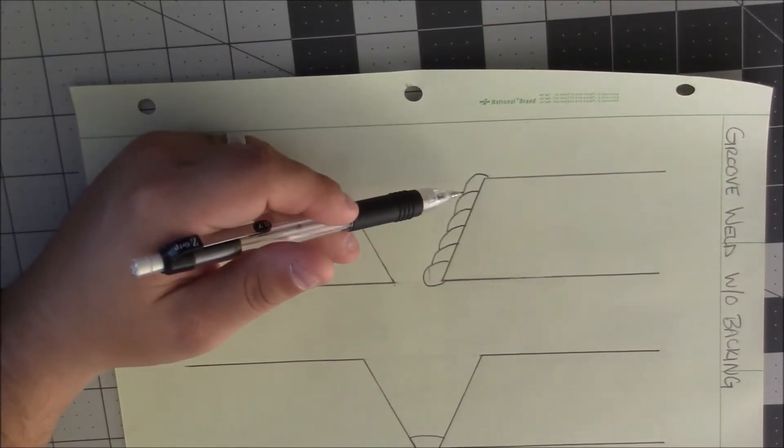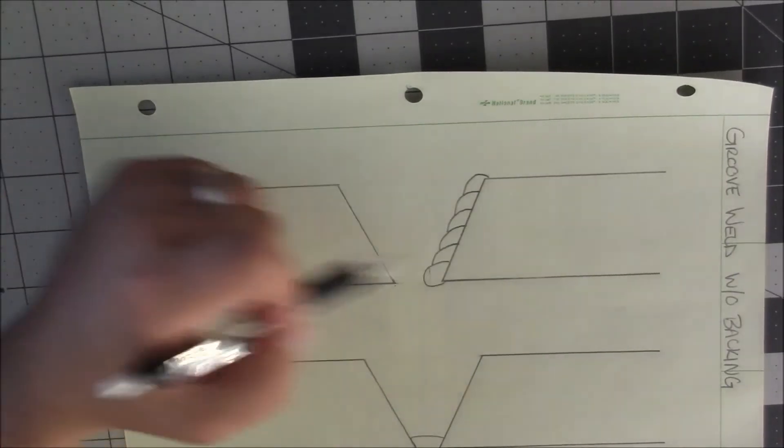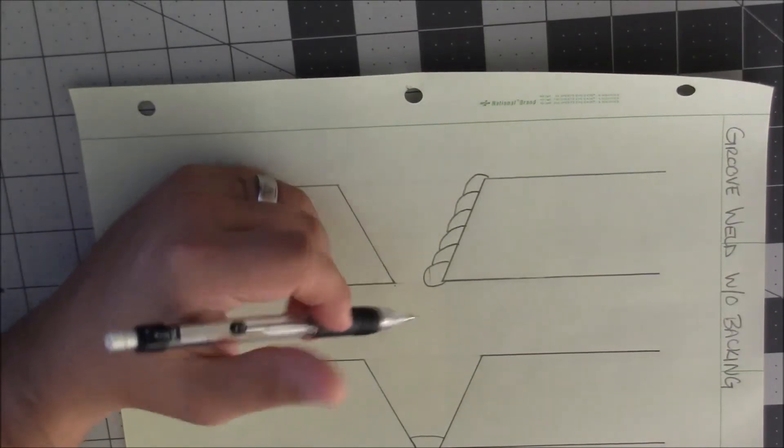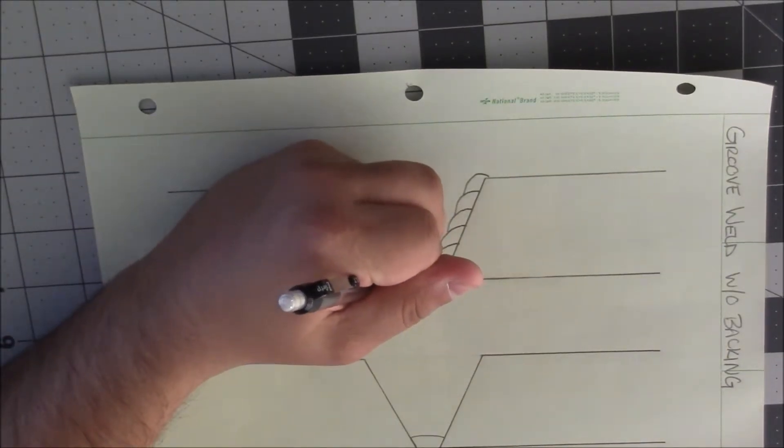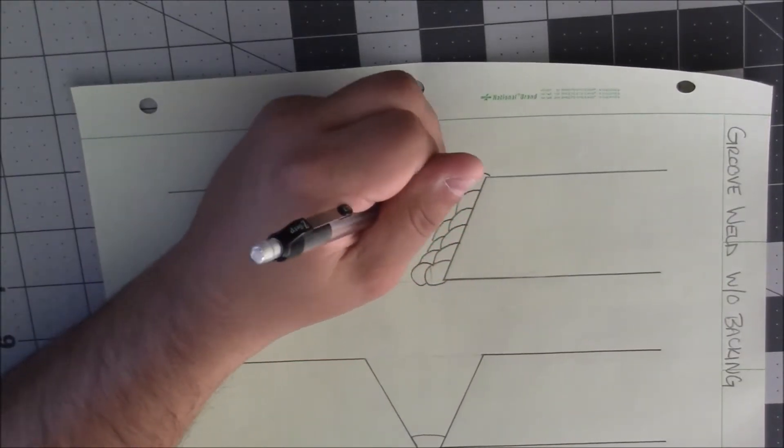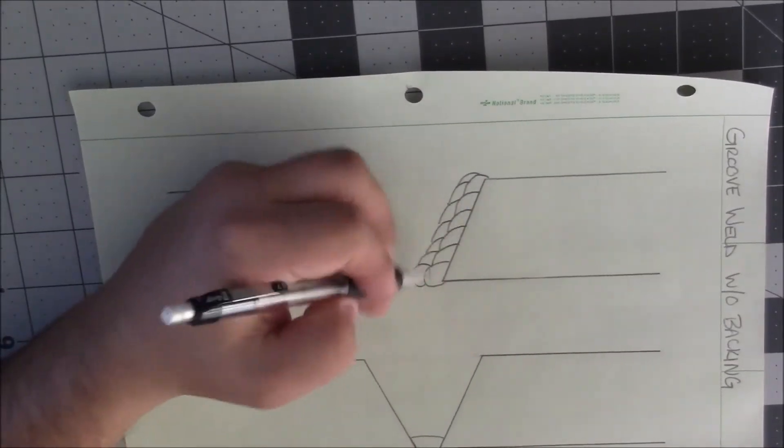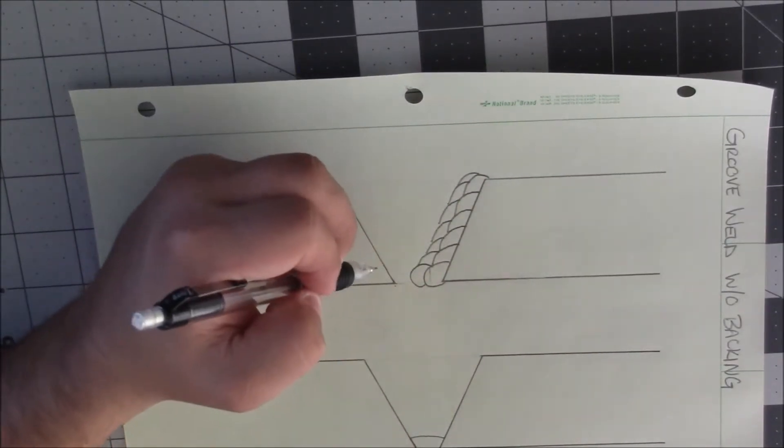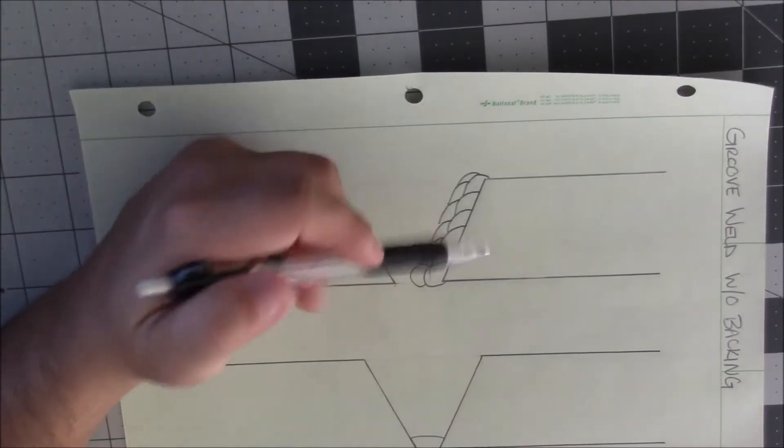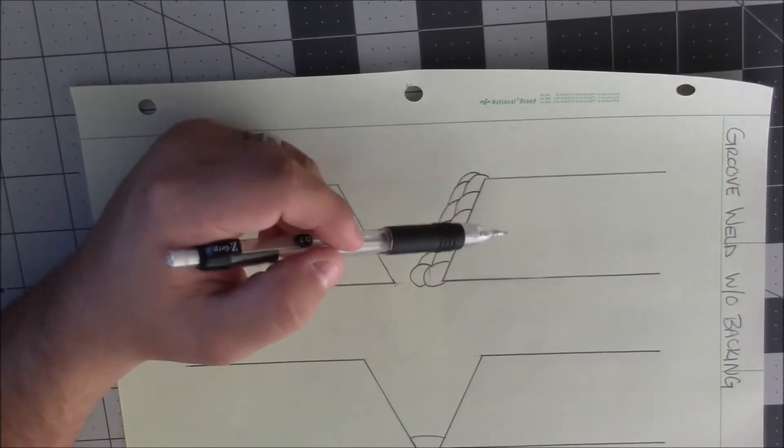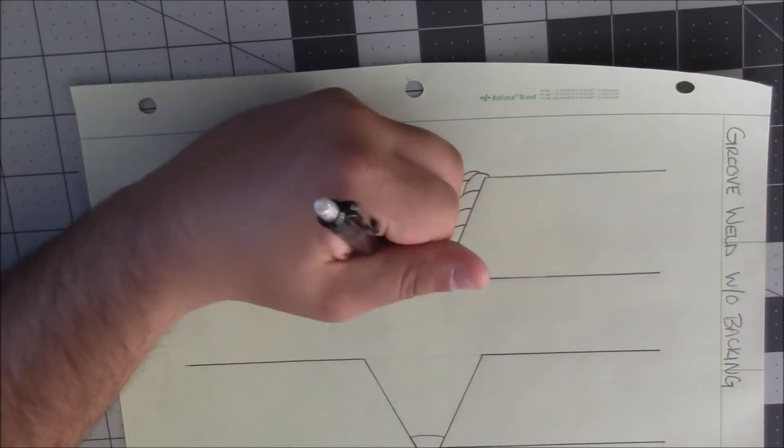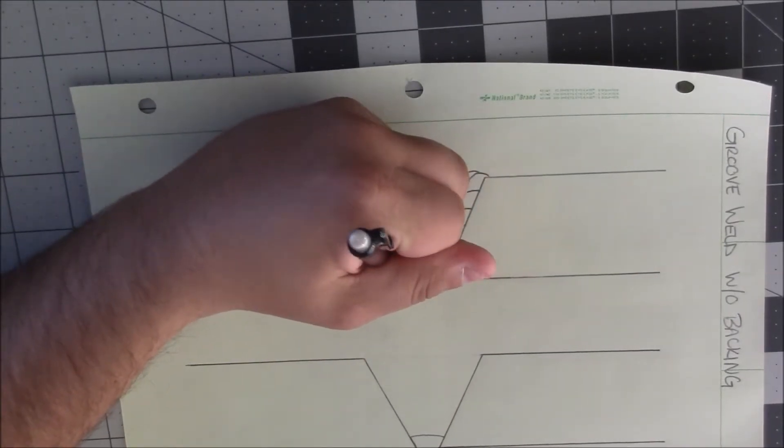Another thing that you might run into, and this is what I would call buttering, is when you have dissimilar materials and you kind of want a buffer material, typically a stainless material, and you would put on another layer. What this does is it provides a buffer so that the material you're using from this side to weld over here is not going to have very much admixture with this material. This is for dissimilar type joints, but then you would go in and you would weld your open root here.